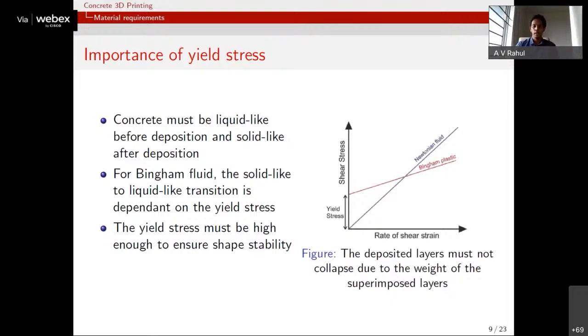To achieve these characteristics, we generally work with the fluid behavior of concrete itself. If you compare the behavior of water with a fluid like concrete, what stands out is that concrete is a Bingham plastic type of material. In a Bingham plastic, as you see in this graph, some initial stress has to be reached before the flow is initiated. In the graph for a Newtonian fluid, even when you apply very small shear stress, you see flow initiating, or a rate of shear strain happening in the material. But in a Bingham plastic material, through the non-zero y-intercept here, a certain shear stress has to be exceeded for flow to initiate in the material.